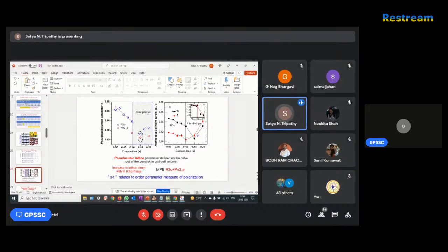So if you go for the primitive one, you have to divide that volume. Okay, so that is a primitive volume, and you have to take the cube root, so that will be a primitive lattice parameter or pseudo cubic lattice parameter. The major thing about using the pseudo cubic lattice parameter is that it reduces down to a cubic size, so that will help us in analysis.